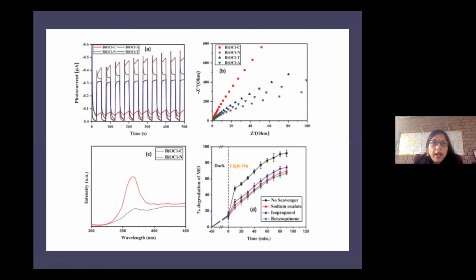And then by photocatalytic activity and electrochemical analysis, it was proven that the separation of electron-hole pairs is greater in the case of the green one. So it means that if we do the photocatalytic activity, it will be enhanced. So we will see that. By the PL and by the EIS Nyquist plot, we saw the smaller circle. So in all directions, it proved that it should have good photocatalytic activity.